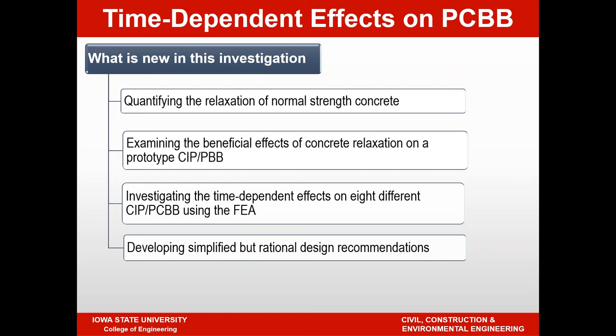the two phenomena are not necessarily identical, and in the past it was difficult to perform a relaxation test. It's easier to perform a concrete creep test. Creep tests have been done for over 100 years. It's fairly straightforward to perform a creep test. Technology today exists for us to perform relaxation tests directly, so we wanted to do that relaxation test directly rather than doing a creep test and reversing the curve.